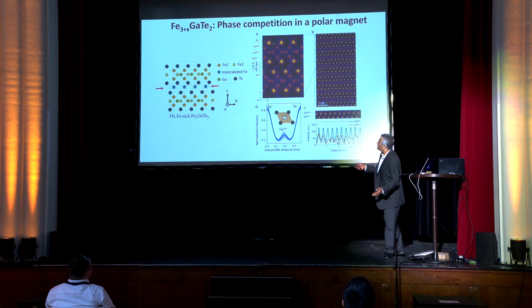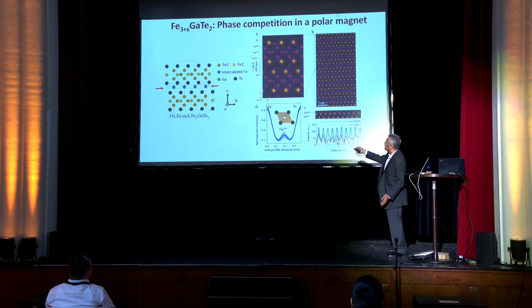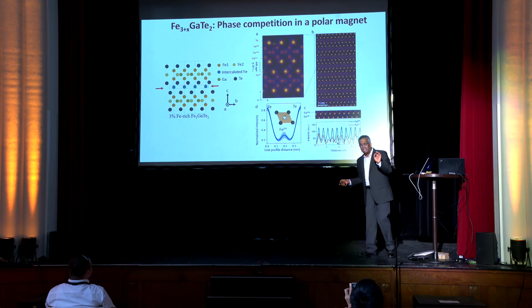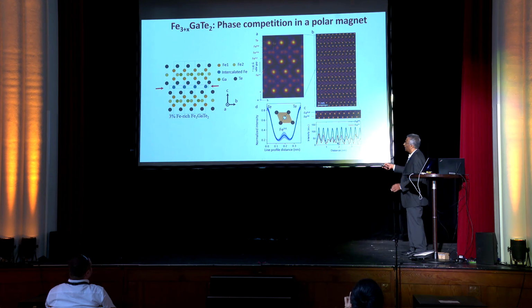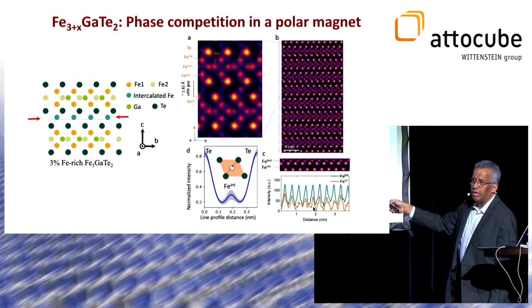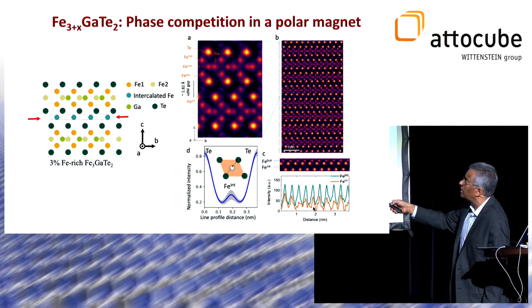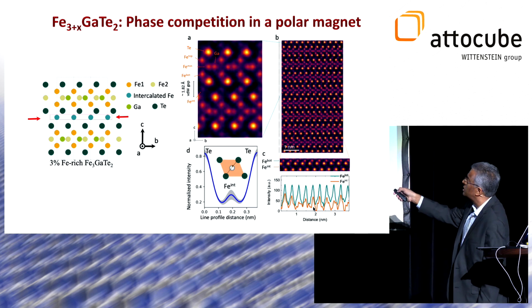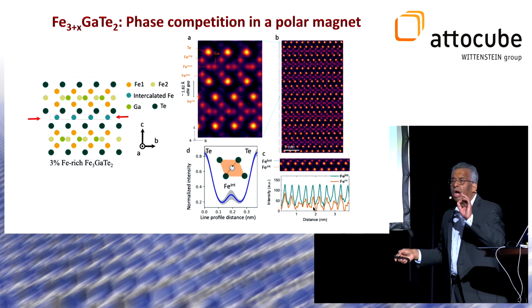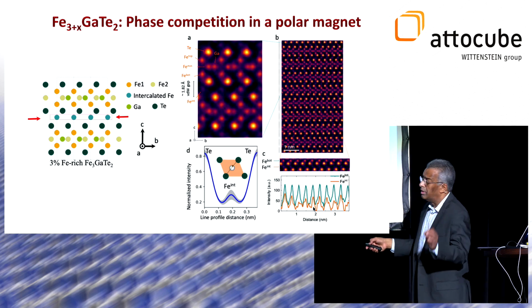A related system is the iron gallium tellurium, but the origin here is a little bit different, but not dramatically. In this case, the original compound, if x is 0, it's quite boring. But if you start to intercalate x, which is iron, into the lattice, you can actually pick up that intercalation in these atomic resolution images. That's right there: there's intercalation of iron, not very uniform, but it is there.